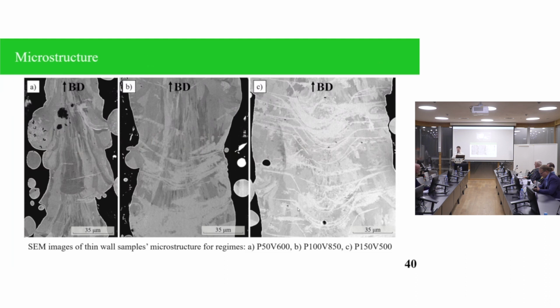Yeah, because this is really a good comment, because in a publication there is a claim that microstructure definitely changes the transformation temperature and so on. But if we look through it even deeper, we can see that the dependence of transformation temperature on chemical composition is much stronger in comparison with microstructure. And this is just an illustration of the texture that I received. This was your other comment. Thank you. So about the second comment.